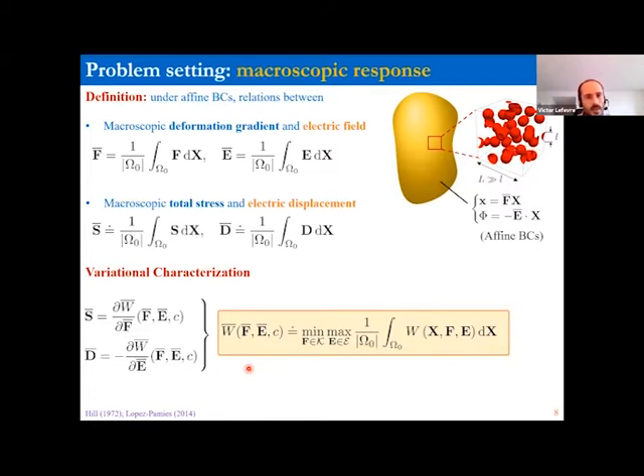So physically, what does this mean? These two partial derivatives, they look very similar to the ones I showed you earlier for the two behaviors of the matrix and the particles. And what they mean physically is that even though this is a heterogeneous material, a composite, it behaves as if it were a homogeneous elastic dielectric with a total strain energy function W bar. And so W bar is simply the total energy density that you need to provide to the system to deform it and to polarize it.